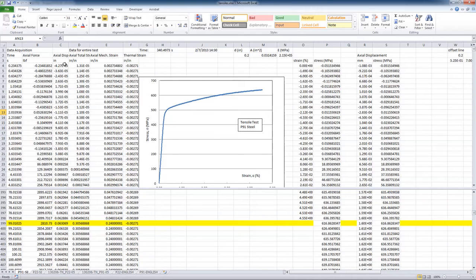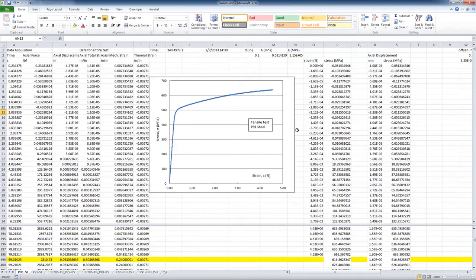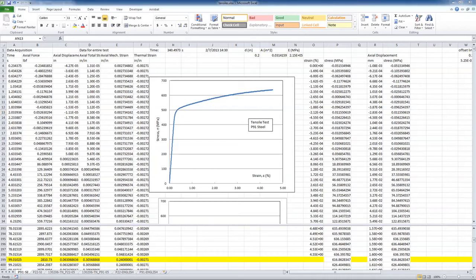Here's time in seconds, axial force, axial displacement — that's the movement of the testing machine piston — total strain, and mechanical strain. This was done at room temperature, so it's an isothermal test. The temperature changed maybe a degree or two, so the thermal strain reading changed slightly, but we're going to ignore it — it's a very small, essentially constant number. Here's the diameter of the bar, the area, and I calculated the modulus of elasticity for this material at about 215 gigapascals.